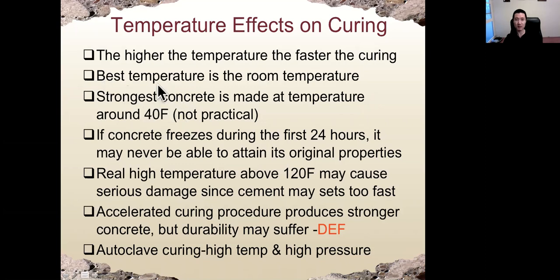But the best temperature is still room temperature because it's very practical - we don't have to do anything to achieve that. If the concrete freezes during the first 24 hours, when the water becomes ice, hydration will stop, so it may never be able to attain its original property. So keep the concrete above freezing temperature at early age.